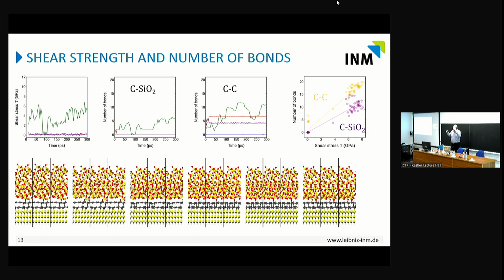So our friction is determined by the covalent bond between the upper graphene layer and the silicon oxide tip, while the number of CC bonds, which is the third graph from the left, actually doesn't matter. I mean, they're there, and they are often co-localized with the covalent bond through the silicon oxide, but they do not contribute to the friction by themselves. So on the most right panel, you can see the number of bonds versus the shear stress, separated for CC bonds and carbon silicon oxide bonds. And you can see that at 0 shear stress, we already can have some of these C-C bonds, but friction is not going up, essentially. Friction goes up as soon as we have covalent bonds to the silicon tip.